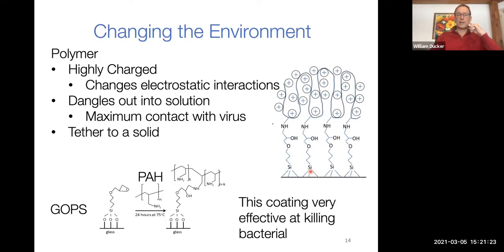So I started thinking about changing the environment. I knew that self-assembly depended critically on the charge balance, and I thought if we used a highly charged surface, we would be able to inactivate the virus. So we worked on engineering a surface where we had a polyelectrolyte tethered onto the solid, and it would dangle out into suspension a long way, because the virus is 100 nanometers in diameter. We needed this film to be 100 nanometers in thickness so it could dangle out and wrap around the virus and inactivate it. This type of approach worked very well at killing bacteria, and we thought it would work.